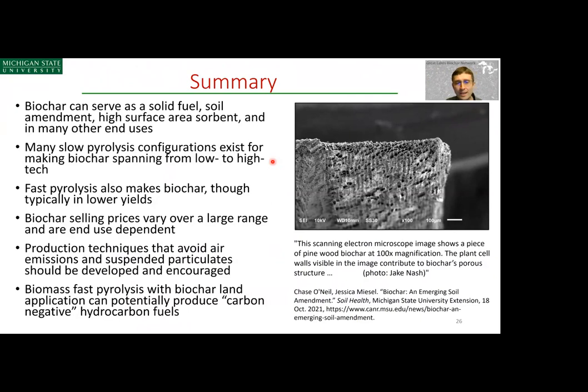Some you can control, some you can't control. Fast pyrolysis also makes biochar, though typically in much lower yields, and the properties of that biochar are substantially different. Selling prices vary over a large range and are end-use dependent, at very least. Production techniques that avoid air emissions and suspended particulates should be developed and encouraged. And biomass fast pyrolysis with biochar land application can potentially produce carbon-negative hydrocarbon fuels.